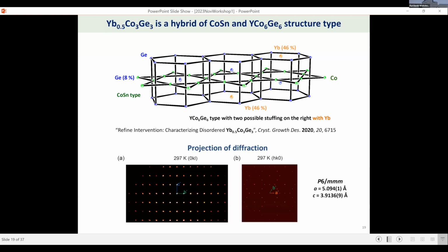Now, this is the single crystal X-ray diffraction. Again, it's nice to have single crystals. We do diffraction measurements at room temperature. We confirm the cell. But again, because of the disorder, it was critical for us to really determine what we have by complementary methods.